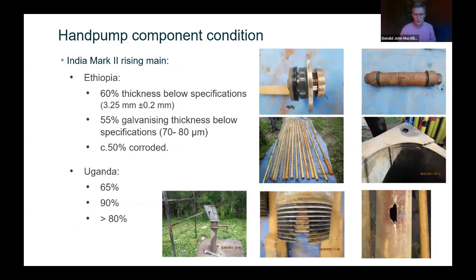Again, just a bit more background results from Ethiopia and Uganda, where we had India Mark II rising mains, and some of the observations that we found. In Ethiopia, about 60% of rising pipe thicknesses were below the specifications, 55% of galvanizing thicknesses were below specifications, and almost 50% of the rising mains and rods that we observed were corroded. In Uganda, that was much higher: 65%, 90%, and 80%. So more than 80% of the pipes and rods we observed in Uganda were corroded. If we can move on to the next slide, please.